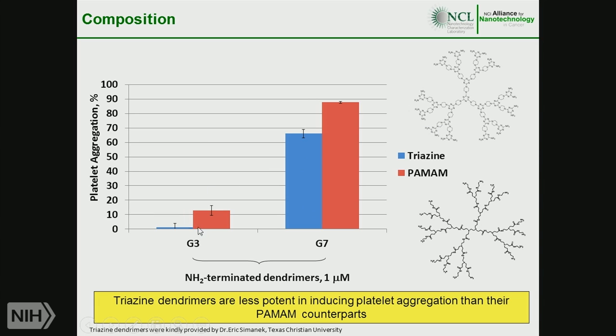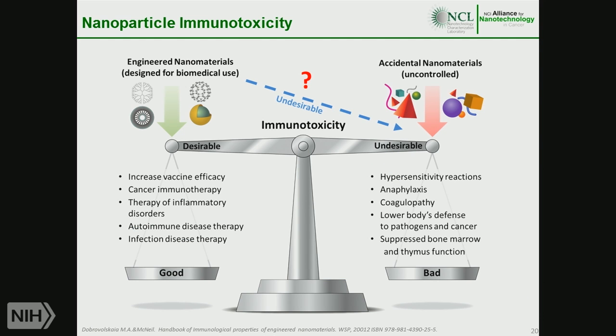We see the same trend in both particles. As the particle size increases and the density of surface groups increases, we see greater biological reactivity. But we see that the triazine dendrimers are less reactive than PAMAM dendrimers. And the way we can explain it is that, at the same generation, the density of the surface groups in triazine dendrimers is lower than in PAMAM dendrimers. Also, these materials have different hydrophobicity, which also contributes to their different biological reactivities.